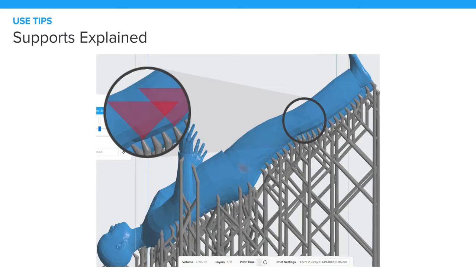One other thing is definitely don't go too gung-ho with your supports. So I just told you, don't space them too far out. Also, don't put them too close together. So keep an eye out for more than 10 supports in a 5 to 10 millimeter radius, because if you have that many supports in a closed area, you're keeping resin from flowing through. Essentially, the supports are creating a forest, and it's stopping the flow of resin. And that can be a problem because it can actually either cause your part to delaminate or cause the laser to fail to harden the resin entirely.